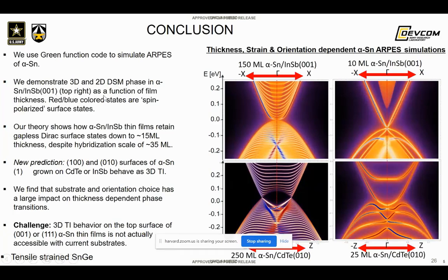and as a function of thickness, quantum confinement converts this Dirac semi-metal phase to a 3D topological insulator, and then a 2D topological, and possibly even a 2D trivial insulator if one can access it experimentally using gates to move the Fermi level, for instance. But nevertheless, this is an interesting thing. The theory predicts that we should be able to observe a number of topological phase changes in these materials by varying primarily the thickness and using strain as another parameter.